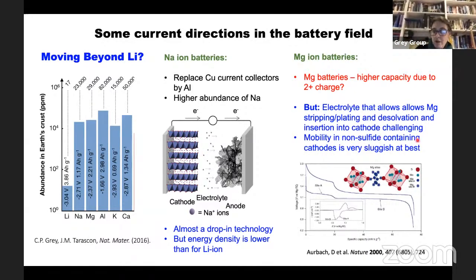And so the only materials that really work very well are the sulfides, and that's because the sulfides have more smushy electron density, so the activation barriers are lower for transport. But you can see this is the magnesium battery, and it's operating at 1 volt. A typical lithium-ion battery operates between 3.6 volts and 4.3 volts. So we've taken a hit of a factor of 3 on that.